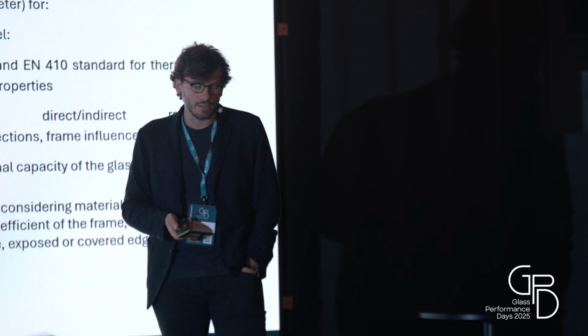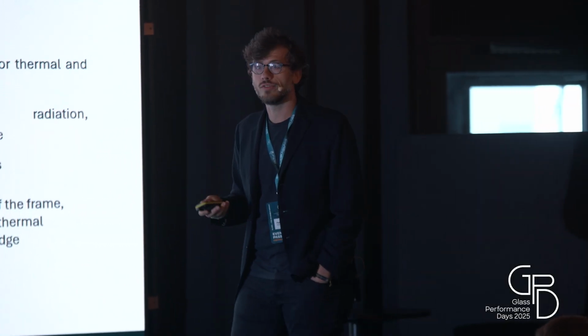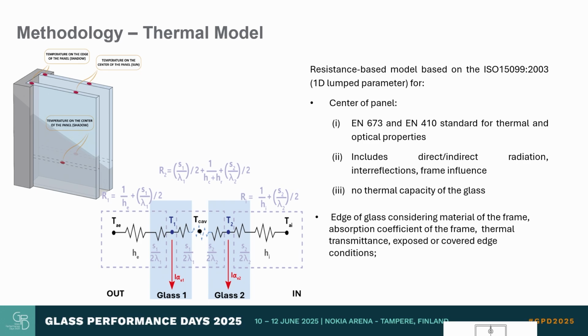So then we elaborated basically two models. These are both resistance models, so one-dimensional lumped parameter thermal models. There is one model for the center of the panel and different models for the edge of the glass. The center of the panel model considers the absorbed solar radiation in the different glass layers, of course, due to direct absorption and secondary interreflection between the different glass layers, and the surface transfer coefficients are divided between radiative and convective ones, differently from the French standards, but it doesn't consider the thermal capacity of the glass, so effectively every hour of evaluation is separated from the other.